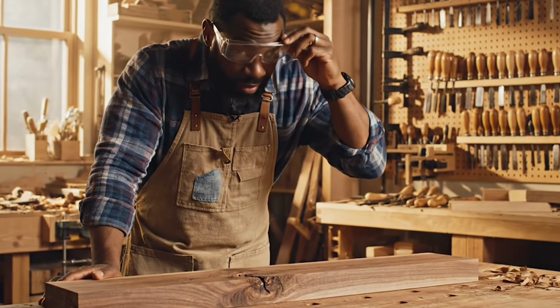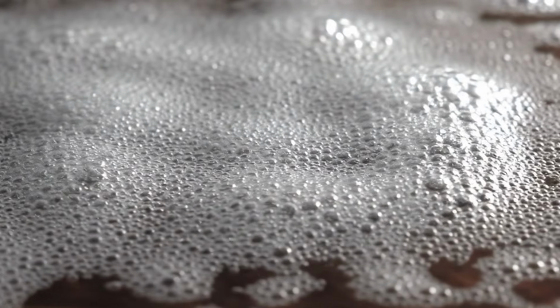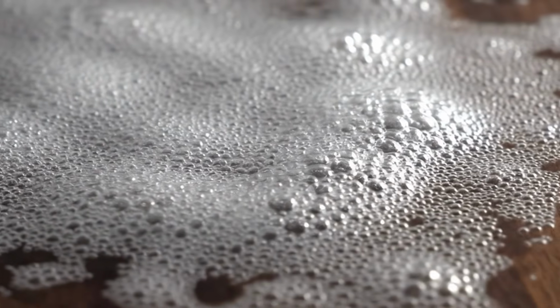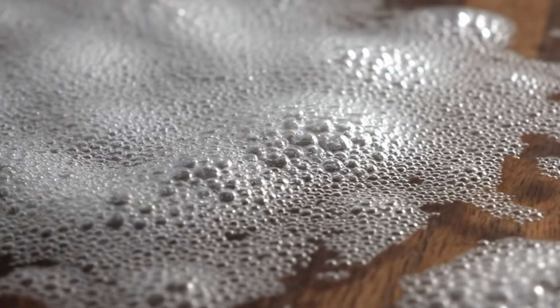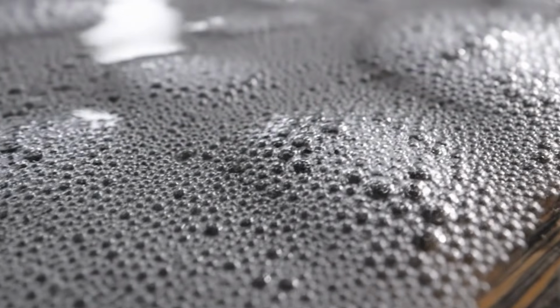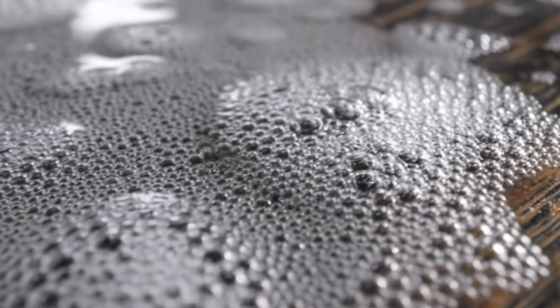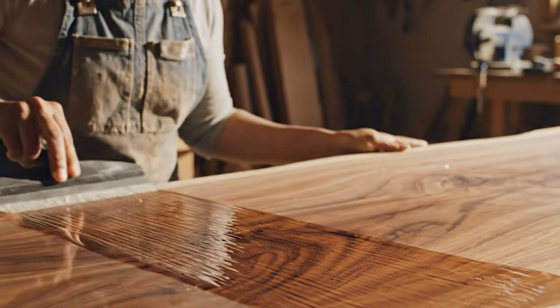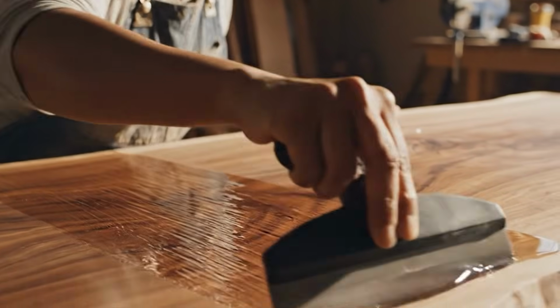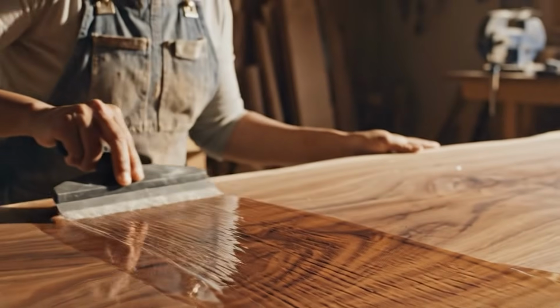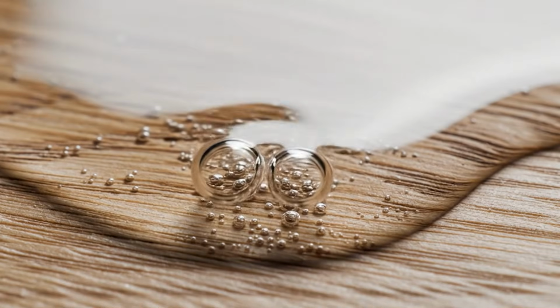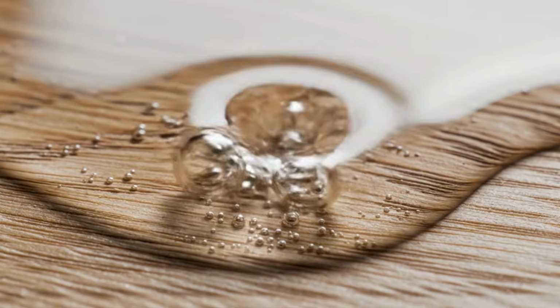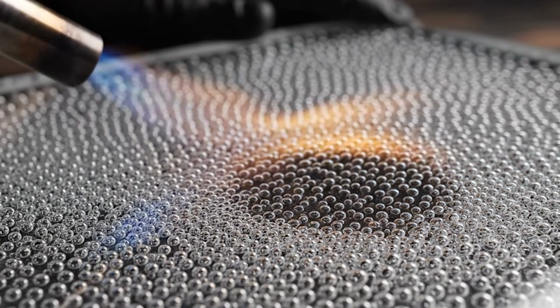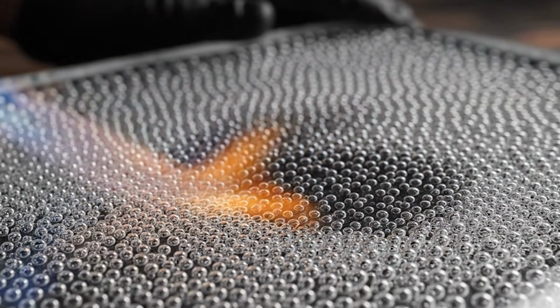Let's talk about some common problems you might run into and how to solve them. First, bubbles trapped in the cured epoxy. This is the #1 complaint I hear. It's usually caused by pouring too thick too fast or by air escaping from the wood grain. The fix is that seal coat I mentioned earlier. Always pour a thin seal coat first and give it time to capture those wood grain bubbles before your main pour, and use your heat gun or torch diligently during the first couple of hours after pouring.